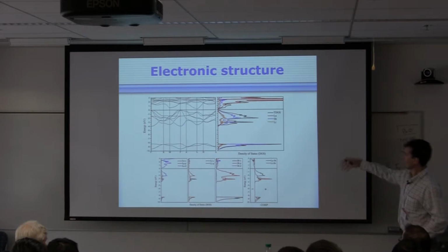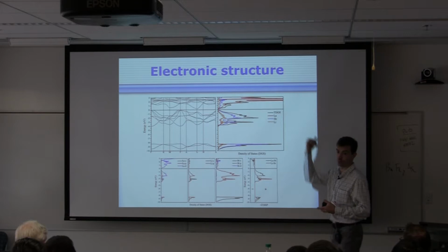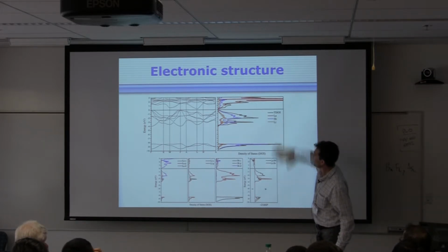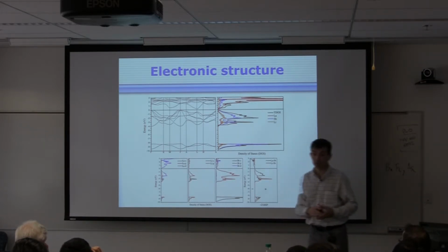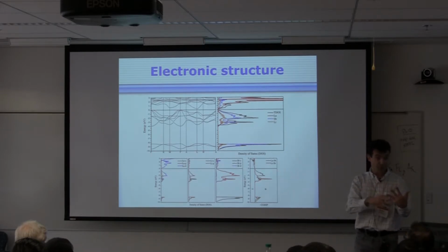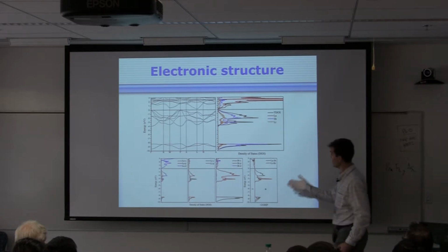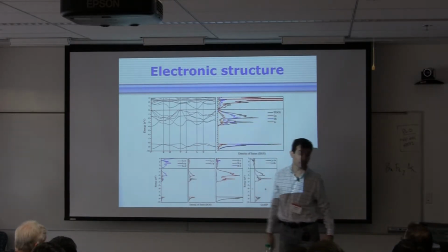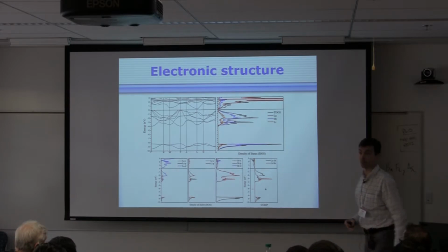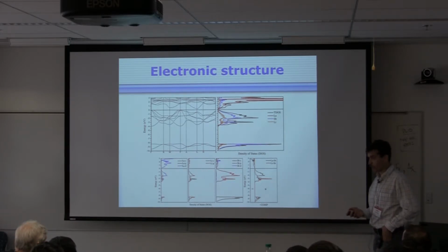Of course, we can do DFT calculations. And now that we know that the structure is not 1-2 but 1-3-2, we can see that everything falls into place. You take 3 metals, lanthanum, lithium, antimony, you put them together in the proper ratio, they form the right structure. You open up a small gap, the way it should be. And again, it took some effort to prove it, and I had some resistance to overcome, but it did work in the end. So this paper is now published.